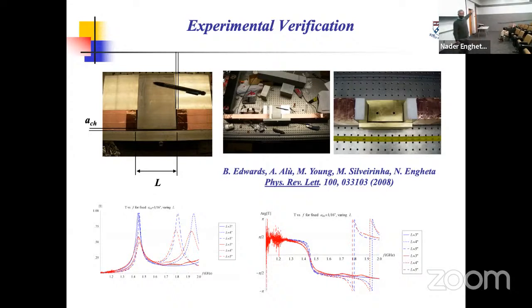Those are the Fabry-Perot peaks. But the first one is the ENZ supercoupling peak. That's the name we gave to this. And you notice, by the way, the magnitude is consistent with our theory, but more interestingly, also the phase of the transmission coefficient is zero. And that's an indication that the index is near zero in that structure.